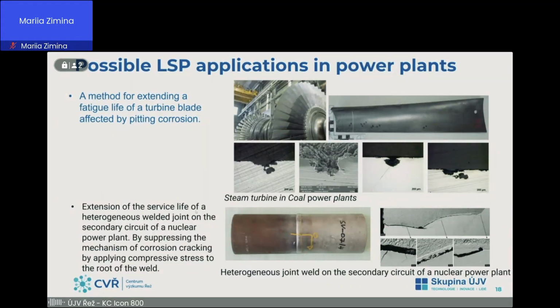The second is extension of service life of the heterogeneous welded joint on the secondary circuit of a nuclear power plant by suppressing the mechanisms of corrosion cracking by applying compressive stress to the root of the weld. There is a problem with stress corrosion cracking between the heat affected zone of carbon steel and the weld. And from the root a crack can initiate and then propagate along the interface.